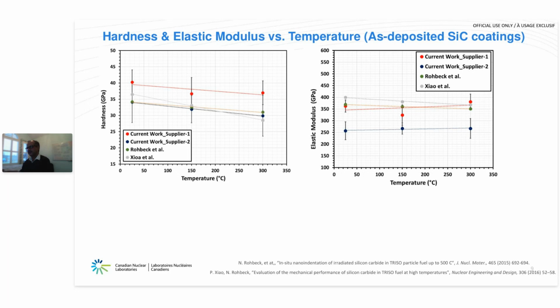Probably the maximum load might be the reason, so we probably need to modify the existing testing parameters. I'm hoping that with further increase in temperature, we'll start to see a decline in the elastic modulus for these coatings. So for supplier 2, the modulus was slightly lower. It's of the order of 250 GPa, and it was again consistent over 300 degrees C, insensitive to the temperature. And again, there are reference measurements for the elastic modulus of silicon carbide coating, and we are within the right ballpark range here.